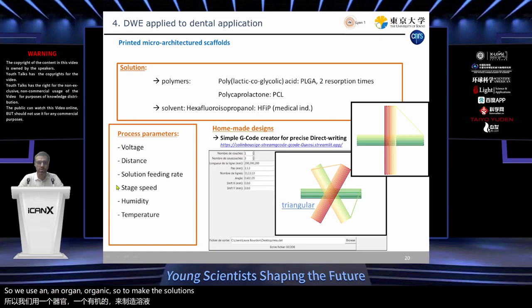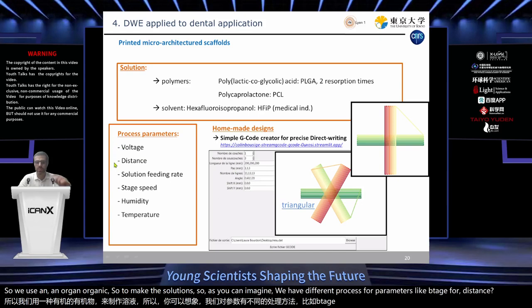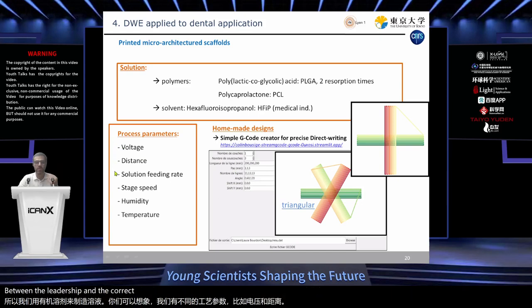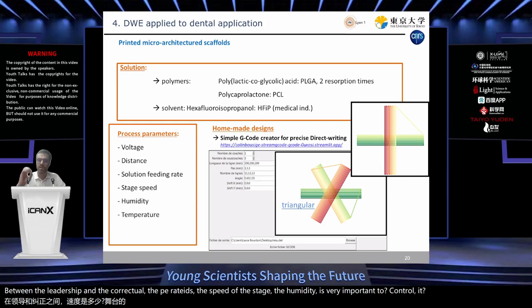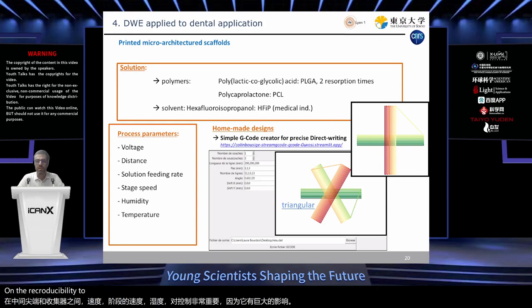So as you can imagine, we have different process parameters like voltage, the distance between the needle tip and the collector, the feed rate, the speed of the stage, the humidity. It's very important to control it because it has a huge impact on the reproducibility of the experiments.